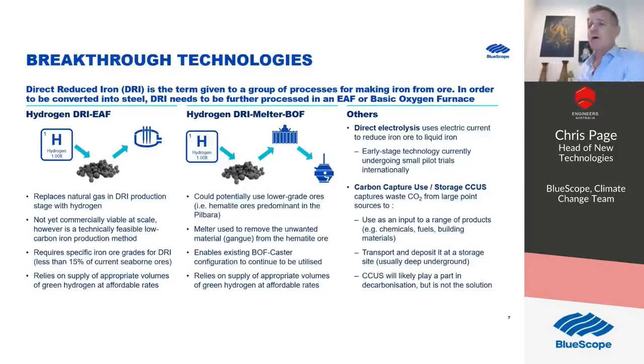Specifically, most of the ore that comes out of Australia is what's called hematite, which is a slightly lower iron content, but has quite a bit more alumina and silica in it. And if you put that in an EAF, you'll create way too much slag, which you'll have to heat up, and you won't get a lot of volume out of the furnace, and you'll be spending a lot of energy melting that slag as well. So for many of us looking forward, we're not going to be able to get access to an abundant supply of magnetite. We're going to look to this DRI melter BOF process.